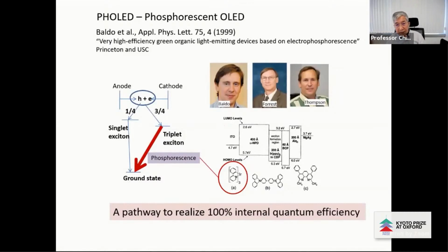And going further, one of the major breakthroughs in organic light-emitting diode came from this group, Steve Forrest, Mark Thompson, and the graduate student at the time, Mark Baldo. So that was the beginning of the phosphorescence OLED. All the work that we did so far was based on the emission from the singlet excitons. And so this has only a 25% probability from the recombination of the electron-hole pair. We lost 3/4 of it through the triplet.